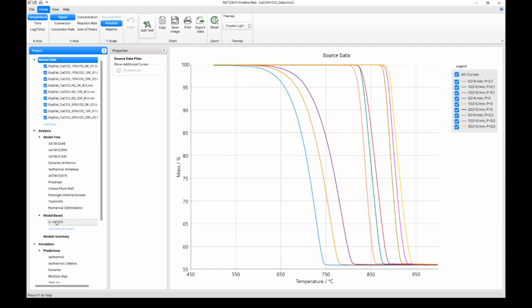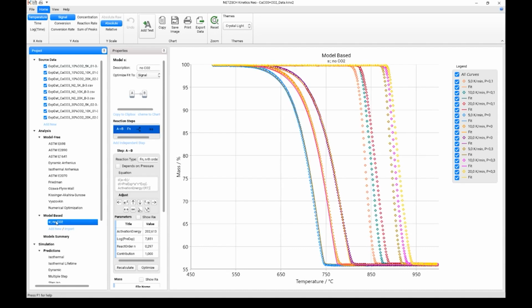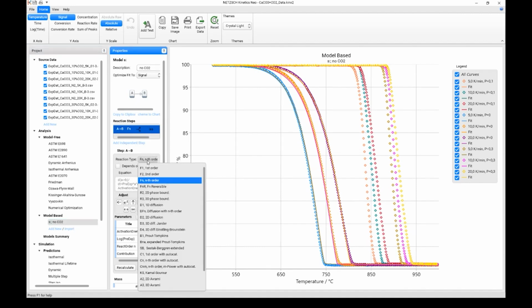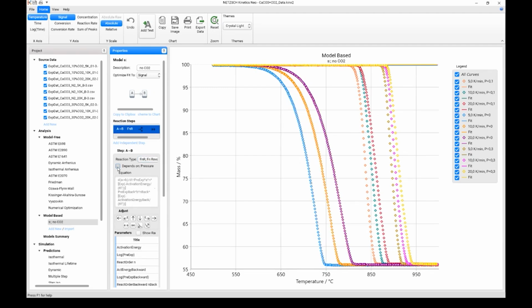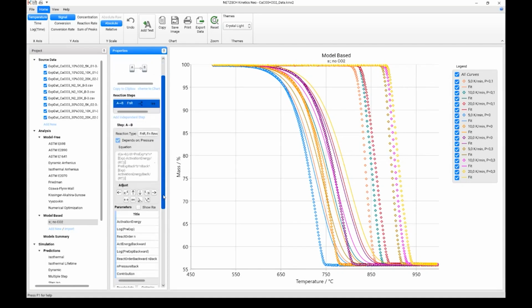Let's go to the model base. Here is our model, which is independent of the pressure. You see all simulated curves are placed here where we have pure nitrogen data. Now we will select a new reaction type, which was not present up to now. It is a reversible reaction where forward and reverse reactions both are reactions of nth order. Then we select depending on the pressure, and after that we will make the optimization of this kinetic model in order to have the best fit for all 9 curves. Now let's see how it works.